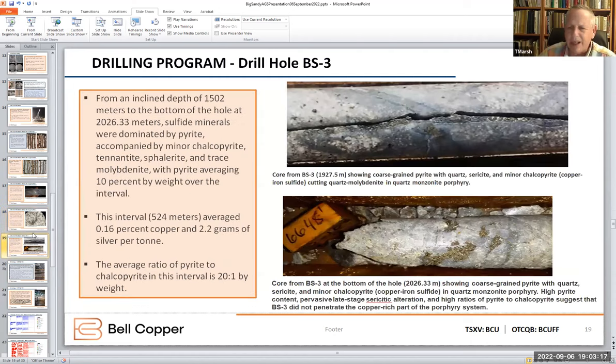Now I'm down to slide 19. All right. Once we got out of the supergene chalcocite at about 1,502 meters, I kept going because there were plenty of sulfides in the interval. We drilled about 524 meters from the top of the supergene enrichment down to the bottom of the hole at 2,026 meters, where the pyrite content averaged around 10 weight percent, so maybe 5 volume percent pyrite. That's a lot of pyrite.